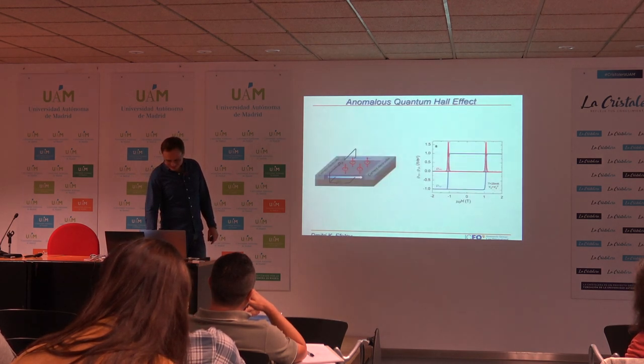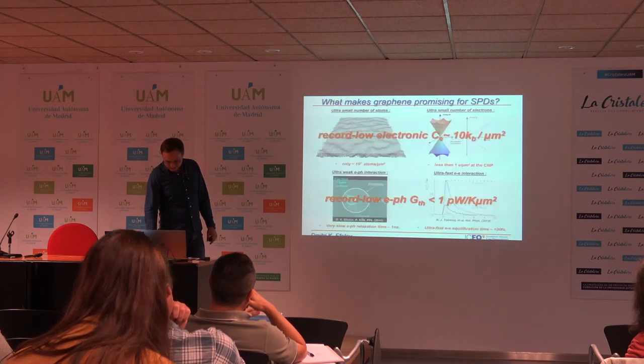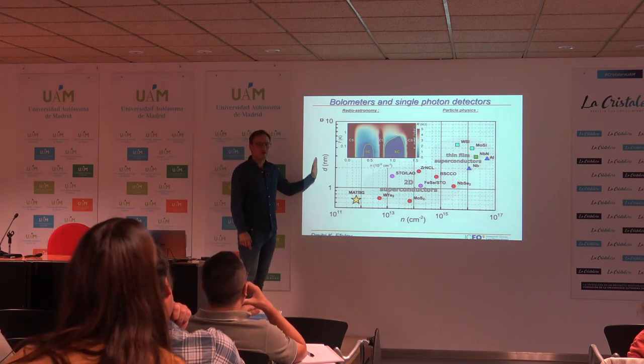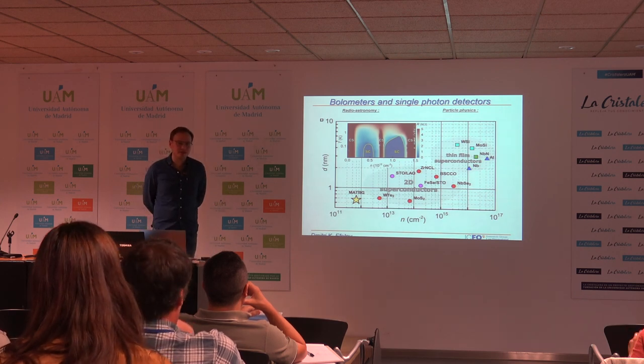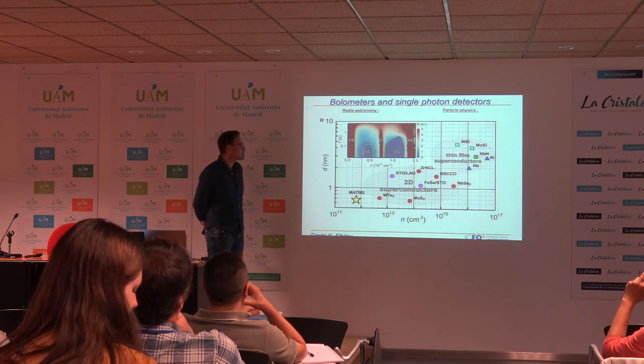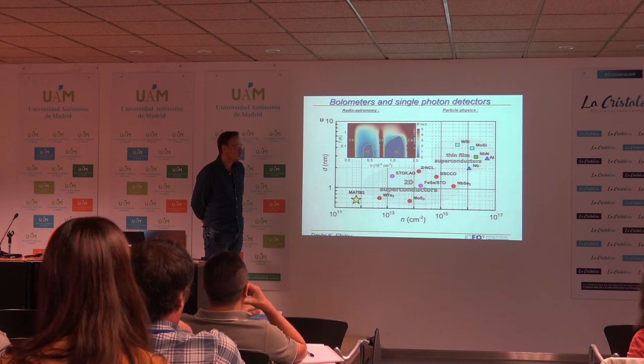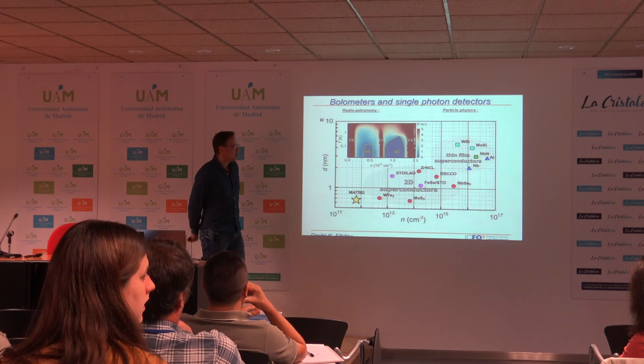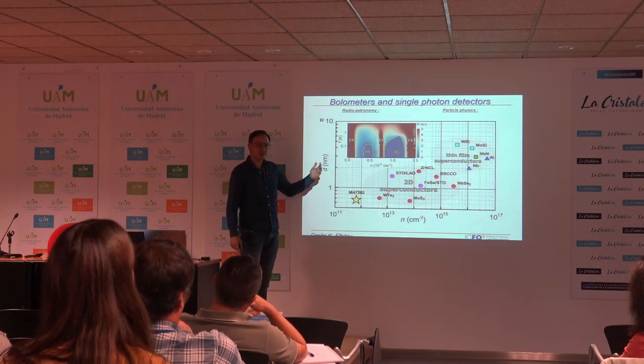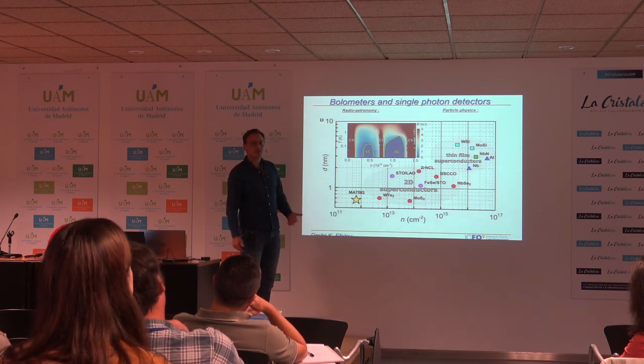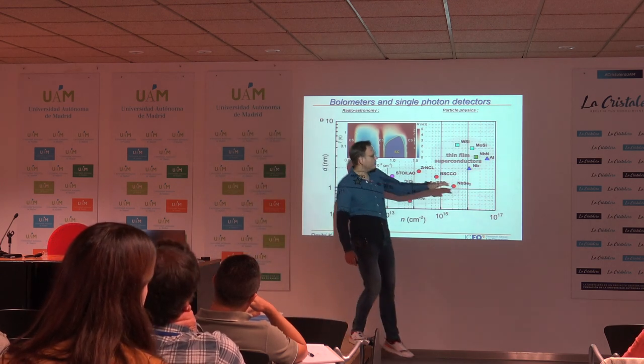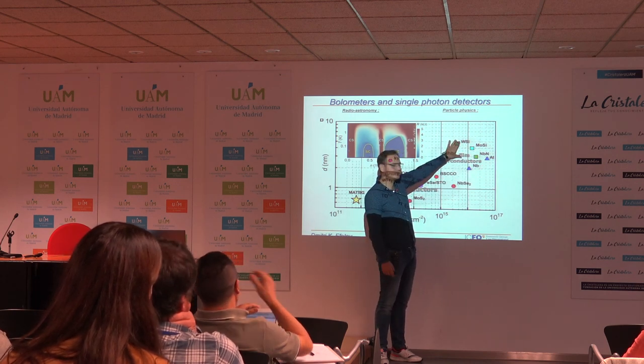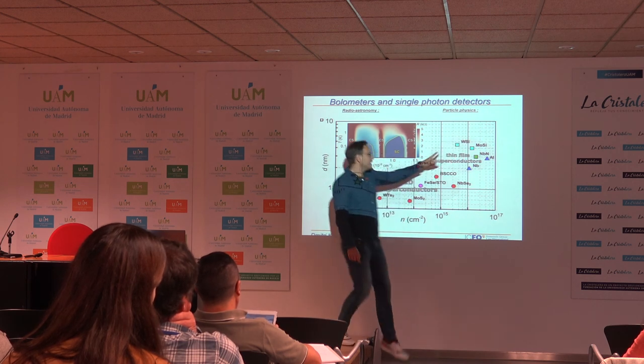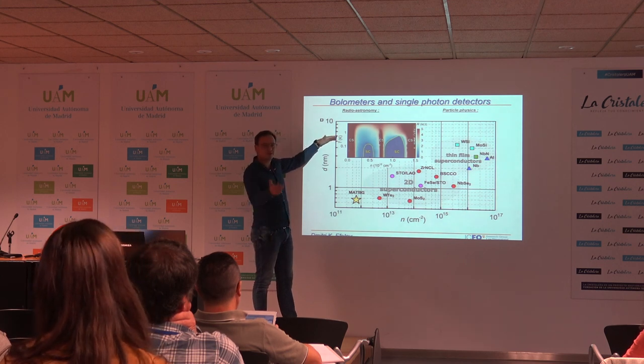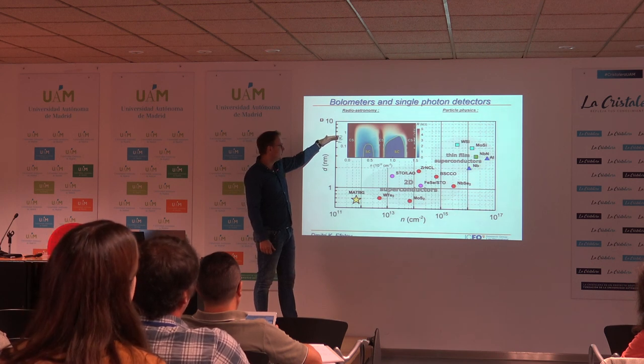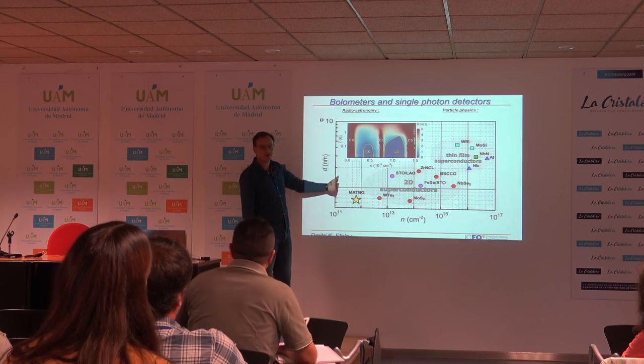So we worked out this graph. As we said, twisted bilayer graphene has the lowest carrier density of any superconductor. We did the job of working out what are the thinnest superconductors you can get, and what are their carrier densities. The usual superconductors used for superconducting electronics, for single photon detectors or transition edge sensors, are usually sputtered superconductors, like niobium nitride, aluminum, niobium. These are well-developed technologies, and people know how to make thin films from them. The thickness is usually on the order of 10 nanometers, maybe 8 nanometers. Graphene is 0.6 nanometers, an order of magnitude thinner than these superconductors.